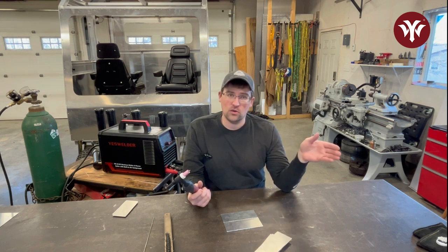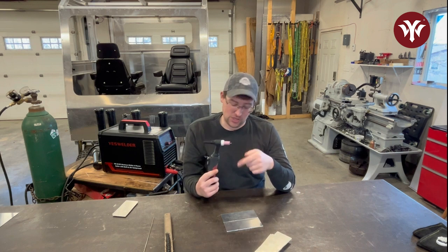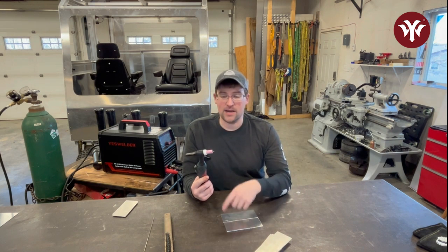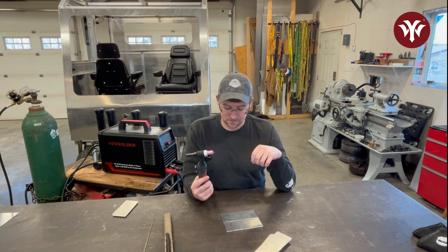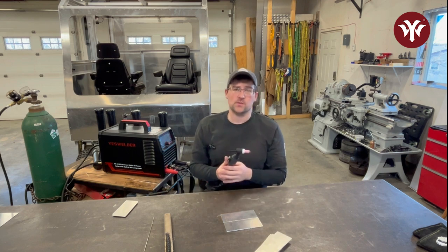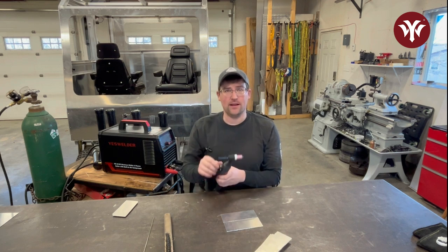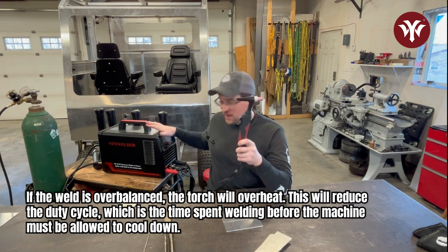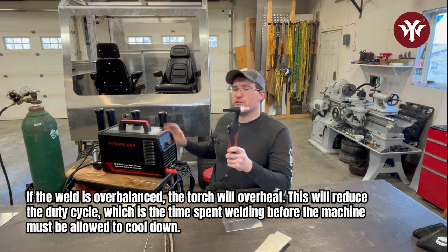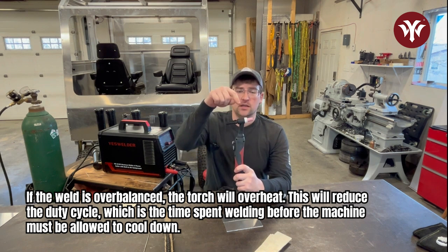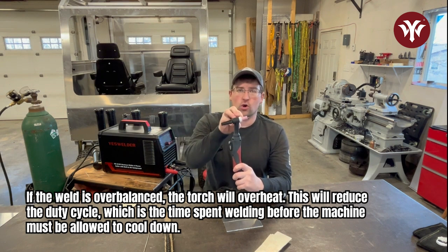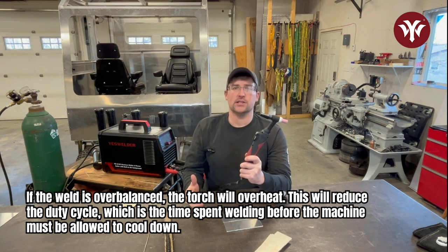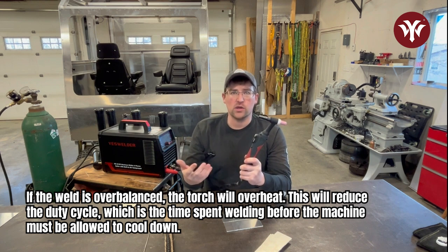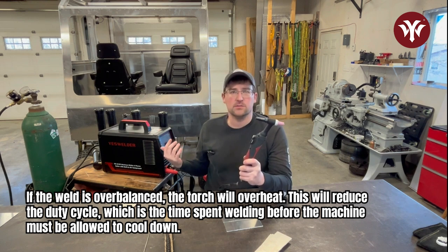I mean, start low, turn it up. You'll notice that you're not getting much weld happening and your torch is overheating, which brings me to the next point. If you're welding with too much balance, the limiting factor of an air-cooled torch like this in an inverter-based machine is going to be your torch. This is going to overheat, which is going to bring down your duty cycle, which is the amount of time you can weld for before you have to let the machine cool down.